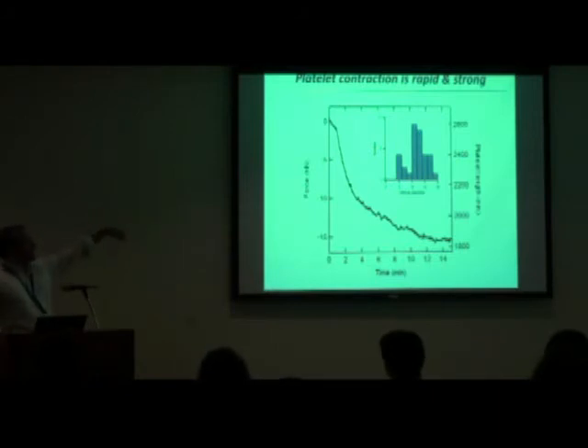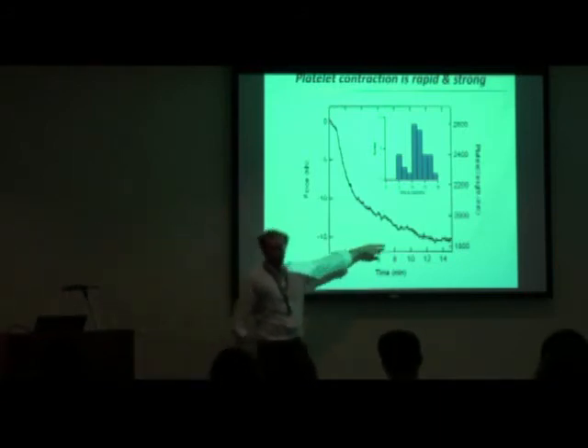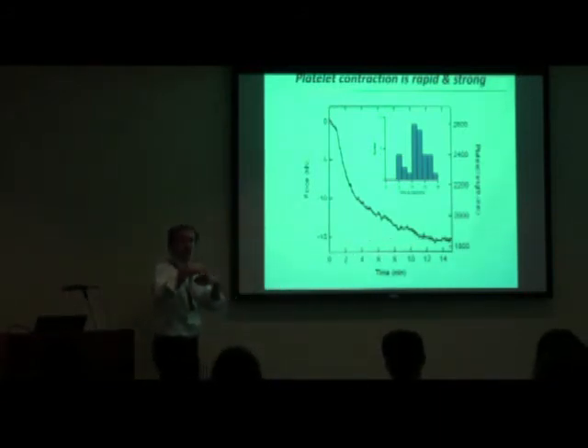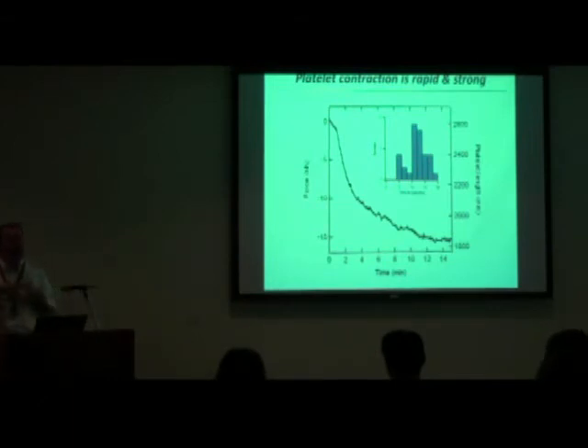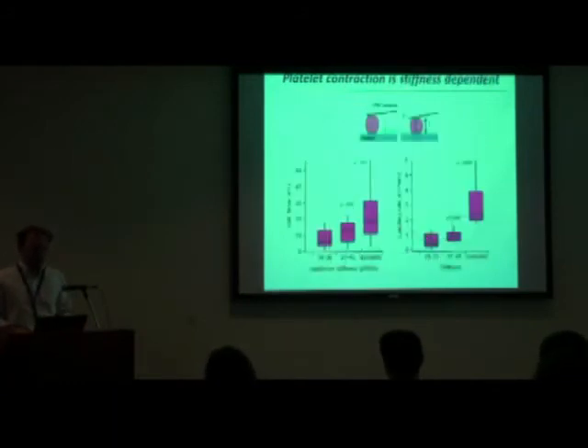Okay, so this contraction takes place, you'll notice, over a relatively short time scale. And so this is a cell that is built to contract and does it once. Once it contracts, it's done. So if we allow it to contract, and then we try to release the force, using an AFM, you have the ability to change the load that's on your sample. And so if you reduce the force on that sample, one might think that it's only just stalled here because it's not strong enough. But if you reduce that force, it doesn't do anything. It doesn't contract anymore. It's done. So it's an interesting structure in that it's a one-shot contraction machine.